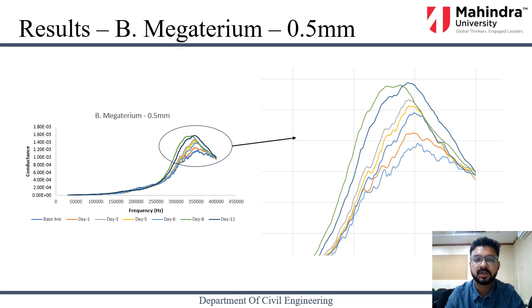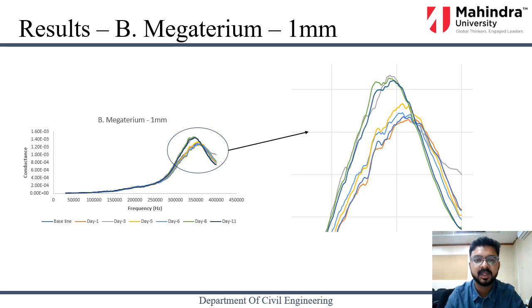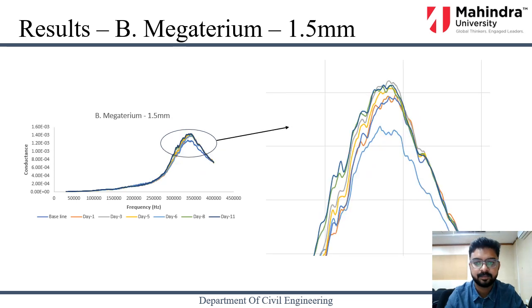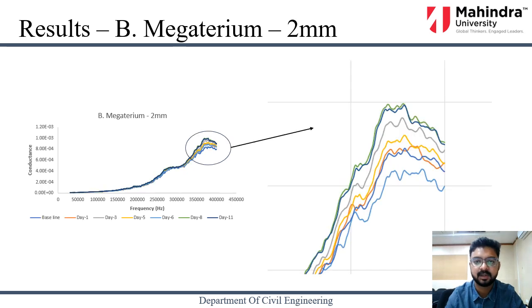This is the 0.5 mm crack acquired data, and here also we can see for the 1 mm data there is a shift in the signature, and this is the 1.5 mm crack signature, and this is the 2 mm signature. So in all these signatures you can see there is a shift in the signature, which says that there is some material which is filling, or maybe some reaction which is happening.